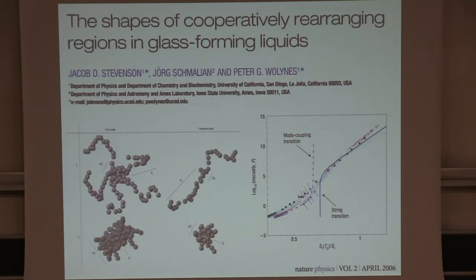One of the issues, which I guess since I have only a few minutes, is, you know, the theory here is what are the shape of these objects? It turns out that, of course, if the surface tension gets lower and lower, then these objects can become less and less compact. And in fact, one can make an argument for where the mode coupling transition should be on the basis of the idea that things are basically percolation cluster-like objects. By the way, that's a theory based on the work of Michael Fisher and was an example of using percolation ideas to get an estimate of a transition in a real system. So the disconnect between percolation and phase transition is not perhaps as profound as one might hope.